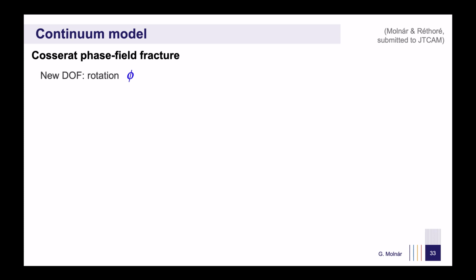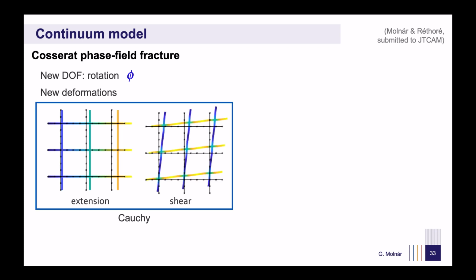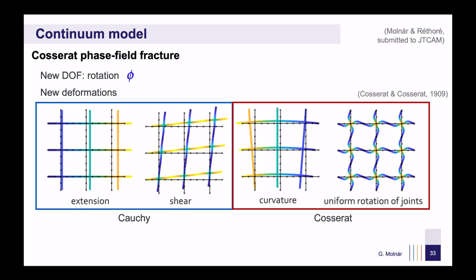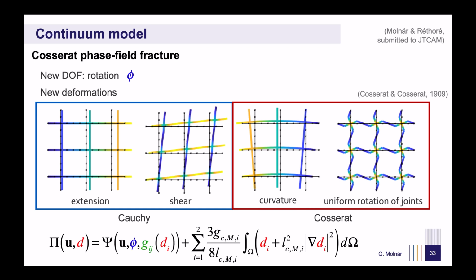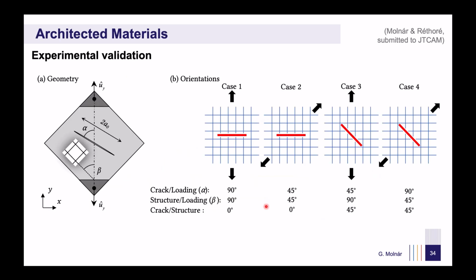To transition to continuum models, we adopted the Cosserat theory, which introduces an additional degree of freedom and independent rotation at each material point. This allows us to incorporate additional deformation effects beyond the classical Cauchy elasticity, such as extension or shear interactions. In this new model, we introduced curvatures and independent rotations, enabling a more refined description of the deformation and failure. Finally, we defined the Cosserat energy and introduced two independent damage variables to account for fracture in two perpendicular directions. Because of the underlying microstructure, fracture in these materials involves a directional dependence, leading to four principal combinations of failure modes.